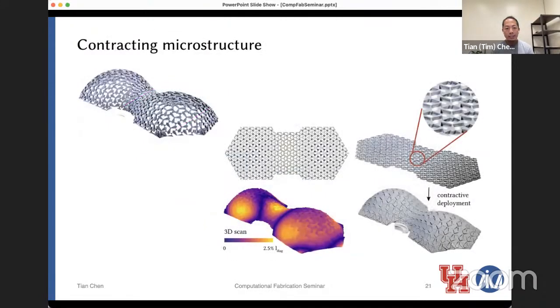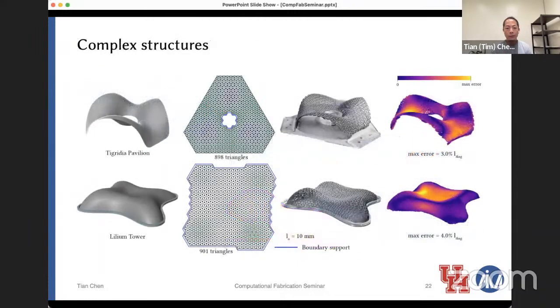There are other techniques that we can use. Since the Gaussian curvature is controlled by the change in length between neighboring elements, we can have different contractions happening between the neighboring elements to have a porous planar state that deploys by contracting into a more or less continuous 3D state. And of course, we can make more complex geometries too. Keep in mind that we do this because the fabrication is so simple. We just take a commercially available rubber sheet and laser cut it, and we can produce these sheets almost in mass.